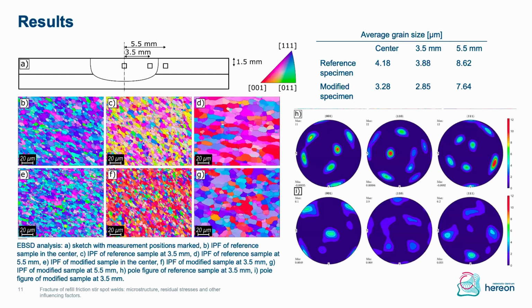And therefore, we had a look at the pole figures of this position. This is both at 3.5 millimeters, while this is the reference specimen and this is the modified specimen. So we see in the reference specimen, we have a shear texture, which is very pronounced. And in the modified specimen, we still see a slight shear texture, but much less pronounced than in the reference sample before. We also saw that we have slightly smaller grains in the modified sample than in the reference sample.